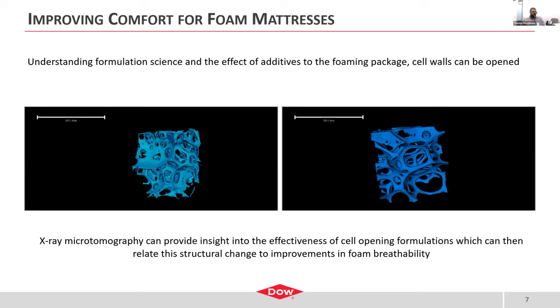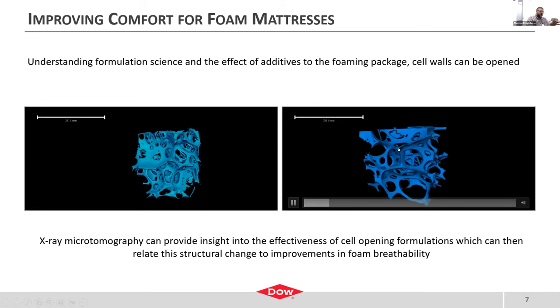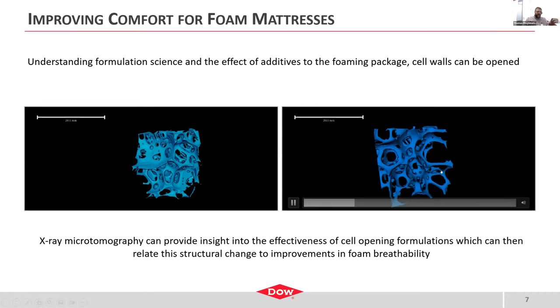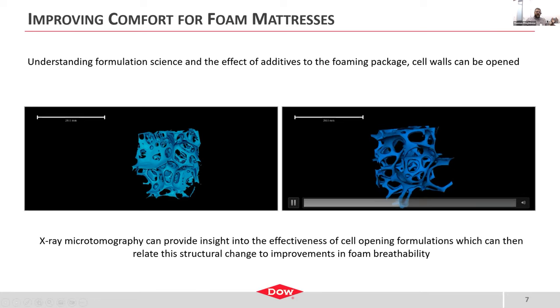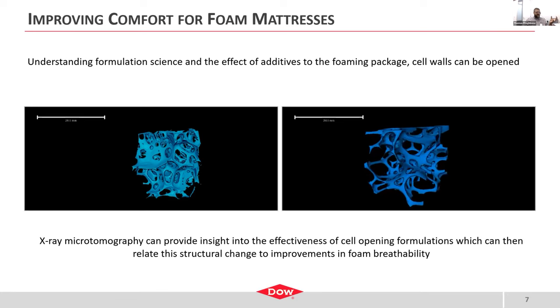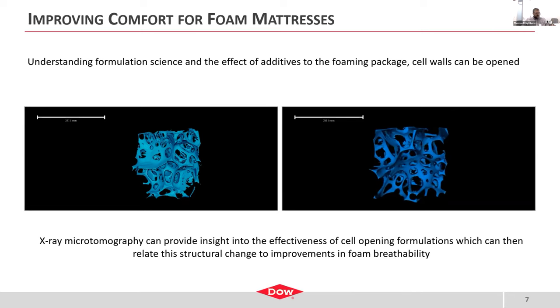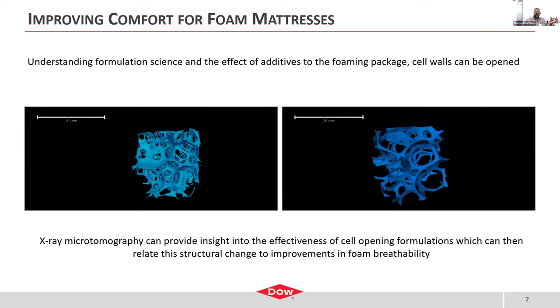At Dow, we've developed a number of surfactant packages that can go into the polyurethane formulation that promote this opening, or what we call drainage of the cells, and you end up with much more open cell walls with a similar density and therefore similar mechanical properties to the starting material, with similar reaction kinetics so that your customer, or whoever is the brand owner of the foam mattress, doesn't have to slow down their manufacturing line waiting for those cells to open and pop.